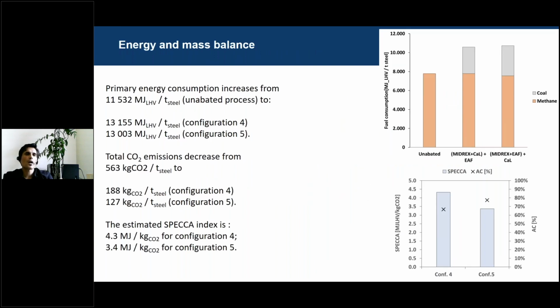Also in this case, we have replicated the same results, but now you can see also the increase of fuel consumption. This is normal, but for the primary energy consumption, this increases from 11,500 megajoule per ton to a value which is greater than the value of fuel consumption. This means that there is no export of energy from the steel mill to the power grid. Nevertheless, the SPECCA index is lower,